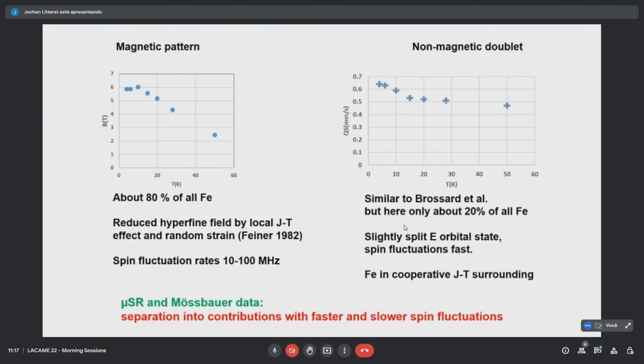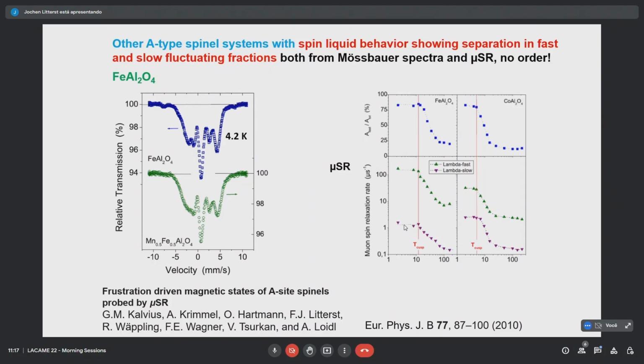So the cooperative Jahn-Teller interaction, what had been before drawn and explained by distortions, now in reality, that's slowed down dynamic magnetic patterns in the spin fluctuations in the range between 100 and 10 megahertz. So both muon SR and Mössbauer will see a separation into contributions with fast and slow spin fluctuations.